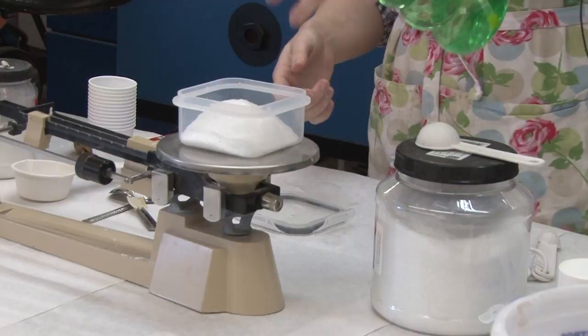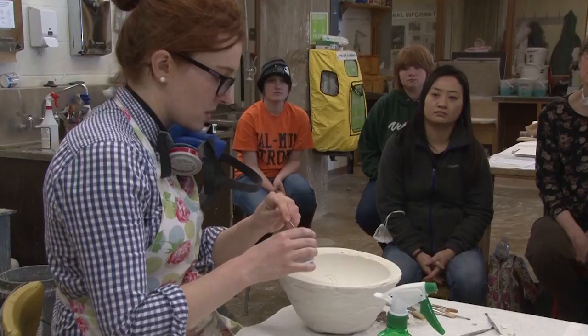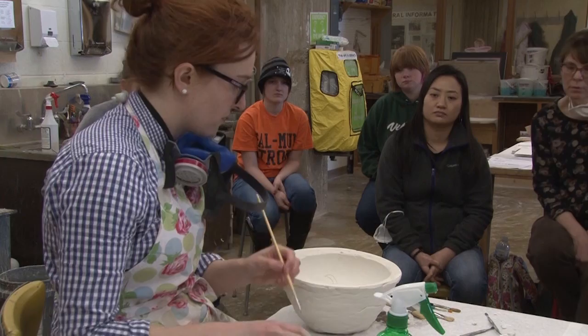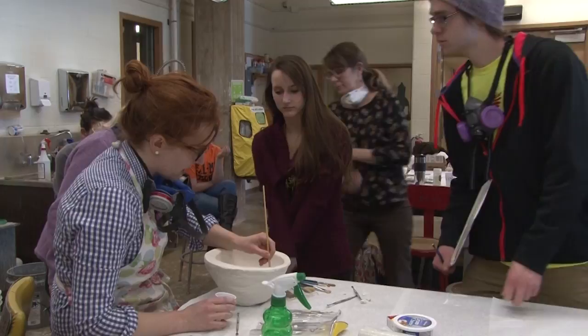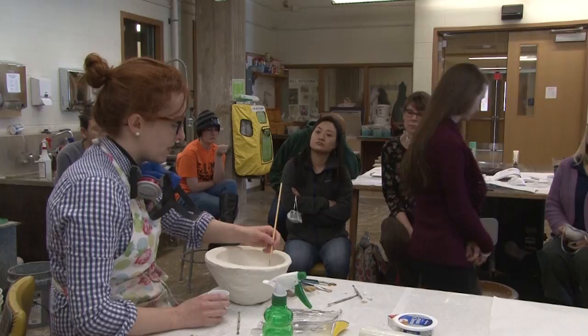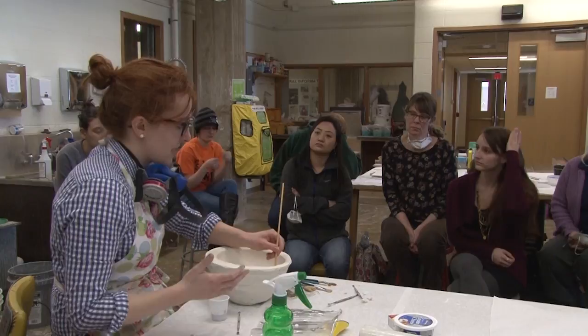When you put your clear glass in, remember to do two or three spritzes of plain water, then put your lid on and shake it. I've mixed pure gray powder with no clear at all, and I'm just going to use a brush to fit it into those grooves. When doing an inlay, you want it fairly thick and not too much liquid, because the more liquid you have, the more it will evaporate in the firing, giving you a lower density of glass.